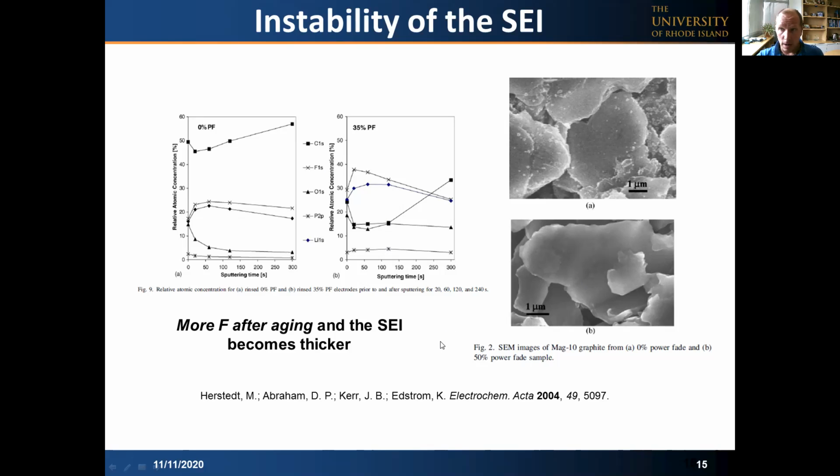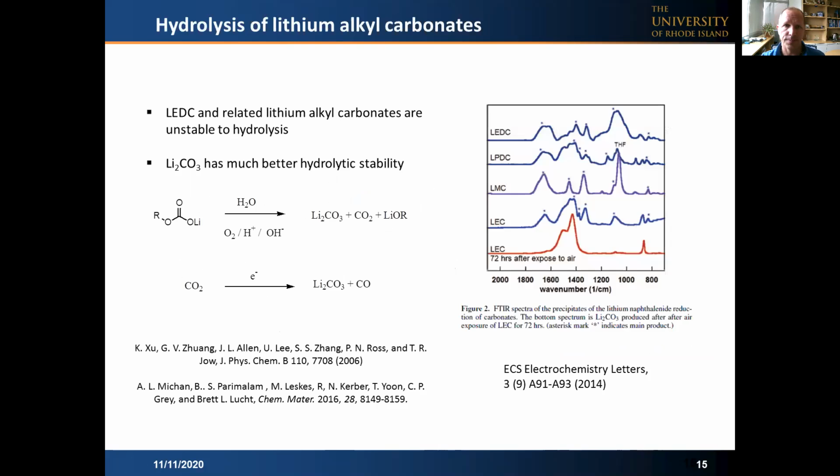But overall, the mechanism of how this happens was not understood at all. So with our understanding of the fundamental initial formation cycling reactions, we wanted to go back and try and understand how this evolution reaction might also be occurring. So with this in mind, we were now able to synthesize independently the SEI components, the lithium ethylene dicarbonate and the lithium propylene dicarbonate and the lithium methyl and lithium ethyl carbonate via the lithium naphthalide reduction reaction.